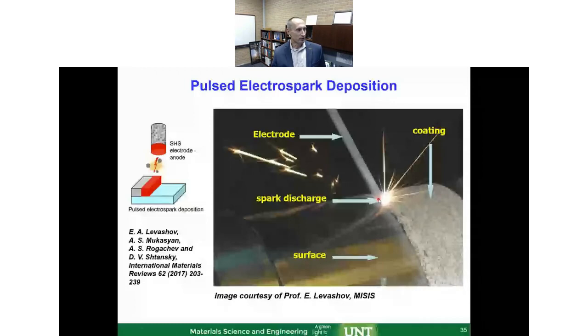For those who are not that familiar, it takes an electrode made out of one of these composite materials which you just saw, and brings it to the working part. In this case, it's one of the shafts. By applying high energy pulses with a high current, regulating these pulses, and sometimes also adding mechanical motion of the electrode, you can very quickly build a thick, metallurgically bonded hard coating on the surface, as shown right over here. The advantage is that you're transferring a large amount of material and bonding it metallurgically to the coating. So you're solving this adhesion problem, as we talked about right in the beginning.